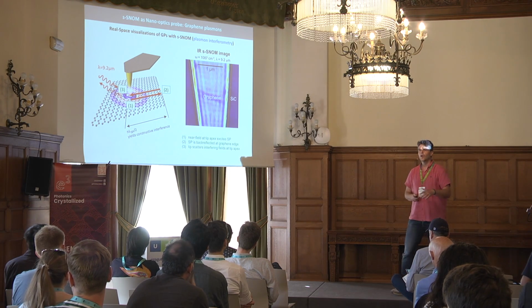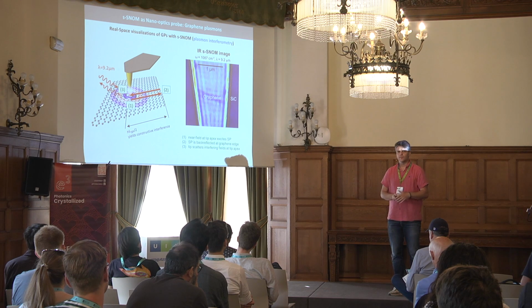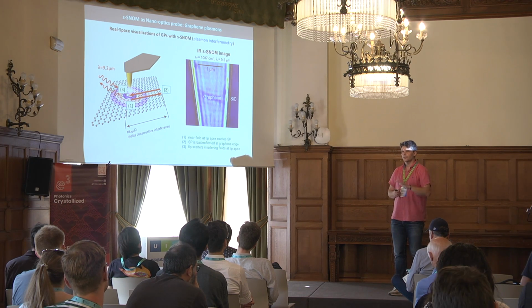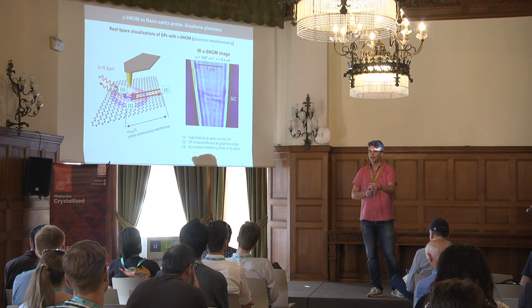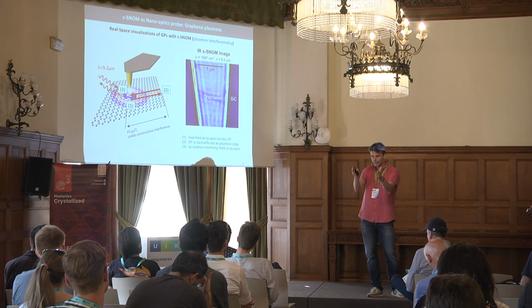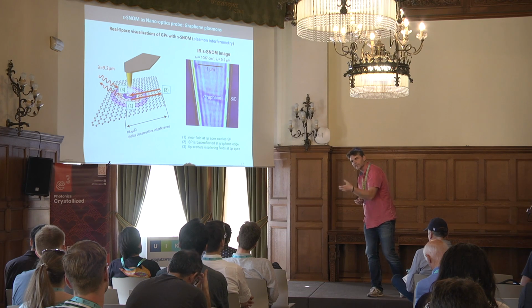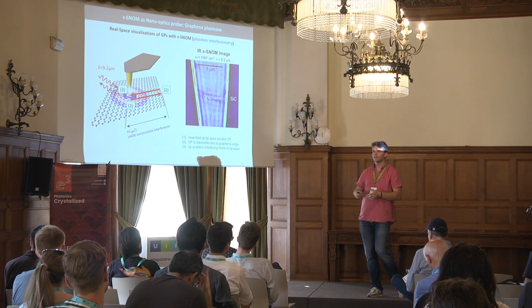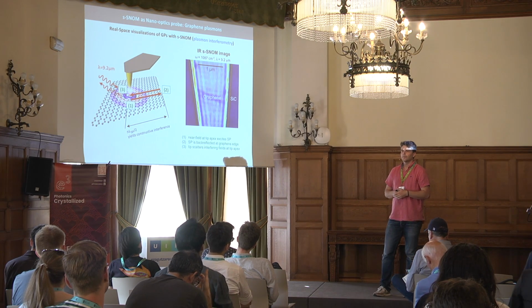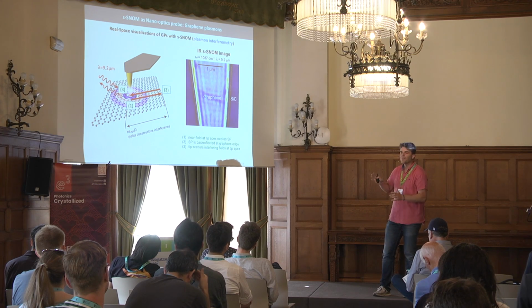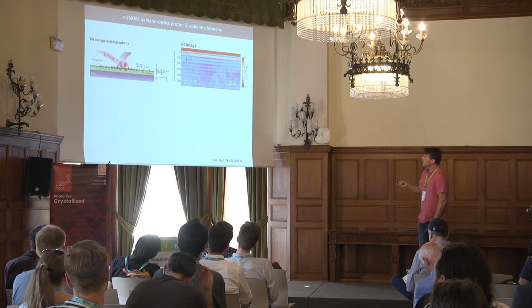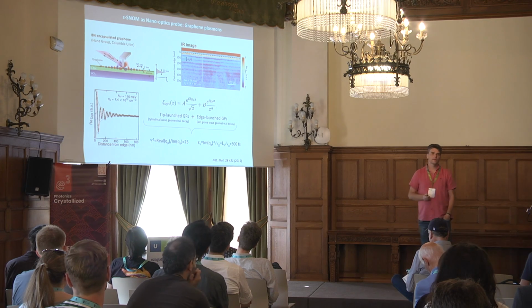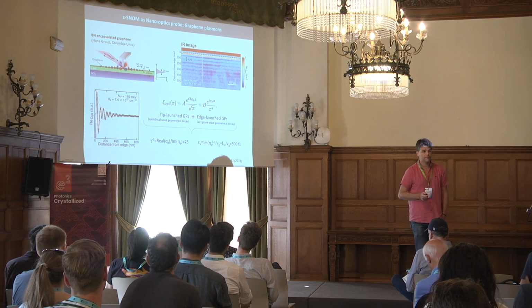I never saw an edge launch graphene plasmons with just a freestanding layer, or just a layer on top of silicon dioxide. But if you put, for example, a piece of gold on top, and the gold has a clear edge, it's like a contact, and then this edge is able to have this localized field, and then you can launch the polaritons nicely, and you can see these lambda periodicity fringes. So we have these two contributions, and we try, okay, let's study them.